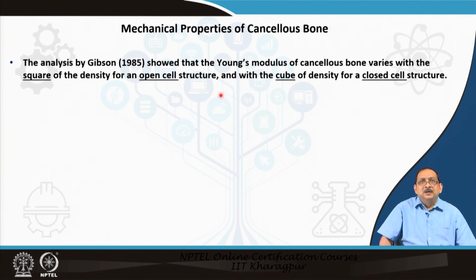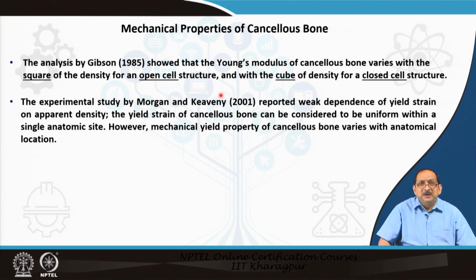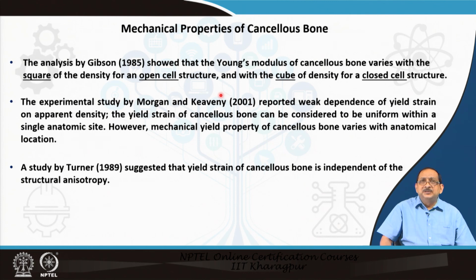The analysis of Gibson 1985 showed that Young's modulus of cancellous bone varies with the square of the density for an open cell structure and the cube of the density for a closed cell structure. The experimental study by Morgan reported weak dependence of yield strain on apparent density. The yield strain of cancellous bone can be considered uniform within a single anatomic site, but the mechanical yield property of cancellous bone can vary with anatomic location. But a study by Turner also suggested that yield strain of cancellous bone is independent of the structural anisotropy.